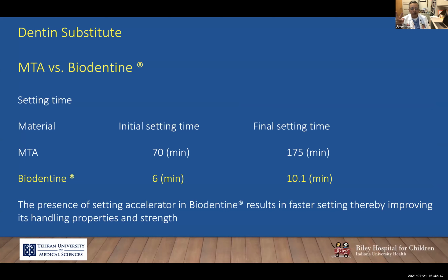Setting time is also different. MTA, the setting time is about 70 minutes, 70. The final setting time with MTA is 175 minutes. Biodentine is 6 minutes, the initial setting time, and the final setting time of Biodentine is about 10 minutes. Why is the difference in times of the setting time? Is because in Biodentine, there is a setting accelerator that results in faster setting, improving the properties and the strength.